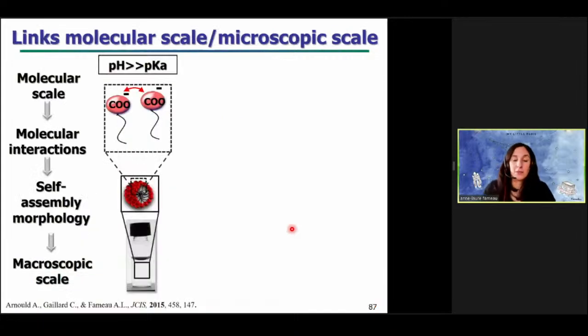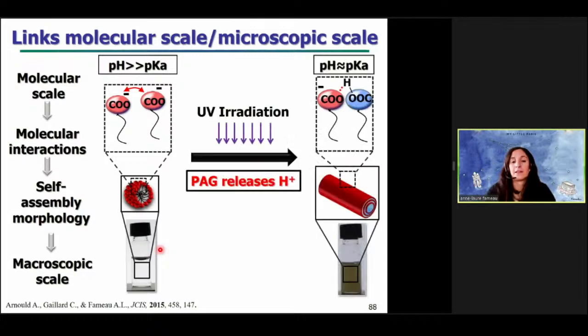So if we summarize the link between the molecular scale and the microscopic scale: before UV radiation, the pH is markedly above the pKa of your fatty acid. All the fatty acids are under ionized state, and they lead to spherical micelles and a limpid solution. Then you put your sample under UV radiation, the photoacid generator releases protons that interact with some ionized molecules, and you observe a decrease of the pH, now close to the pKa of your fatty acid, and you have the two states of fatty acid, protonated and deprotonated ones, that interact by hydrogen bonding. And so you have the formation of your big micron-sized multilamellar tubes, and you observe a turbid solution at the macroscopic scale.